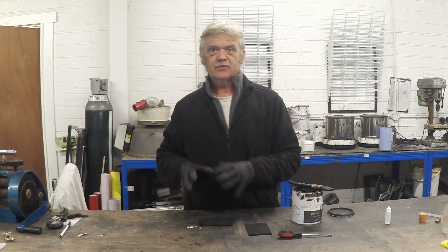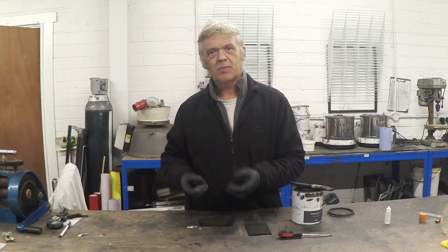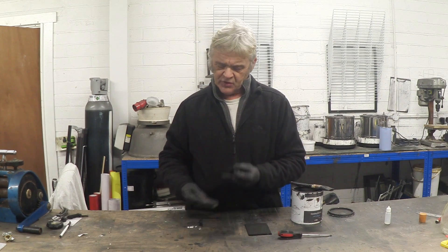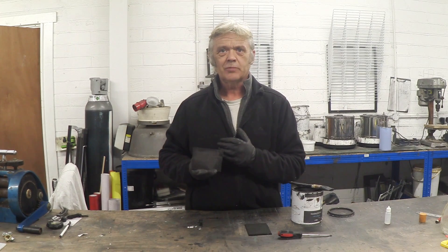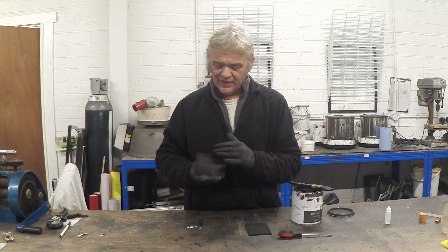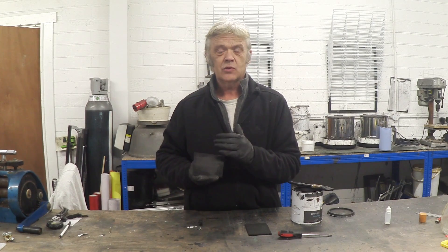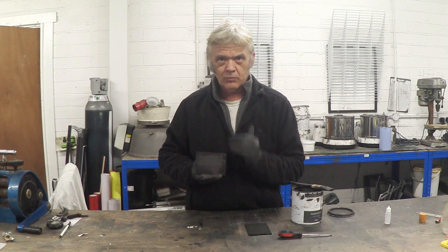There we go. Leave it to dry — we're going to soak it in water, so you have to dry it thoroughly. If you leave it a bit damp, the water will lift the paint. Once it's dried thoroughly it's fine; it's attached itself to the felt and sunk in a little bit. There are lots of little holes in it that we're not seeing — that top surface is now covered with an adherent graphene coating. There's graphite and graphene coating just on the top layer of the felt.